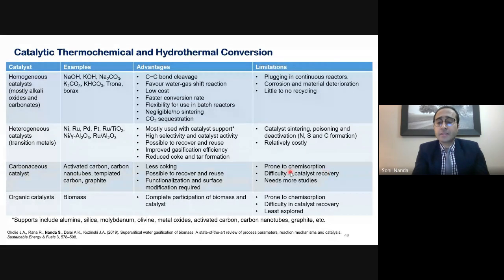But the limitations are they are prone to chemisorption and it is difficult to recover the catalyst, because these are mostly made of carbon, and they will easily mix with the biochar, the solid residue that is obtained from the process. So it is very difficult to differentiate which one was a catalyst support and which is actually a product. That causes some disturbance in the product distribution and the estimation of the solids, liquids, and gases after doing a mass balance.